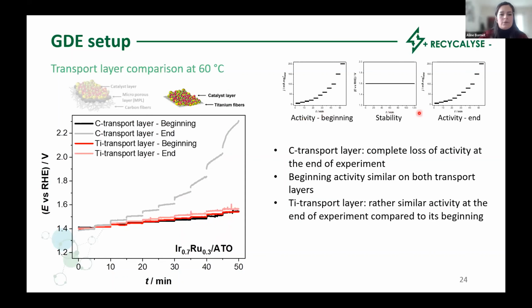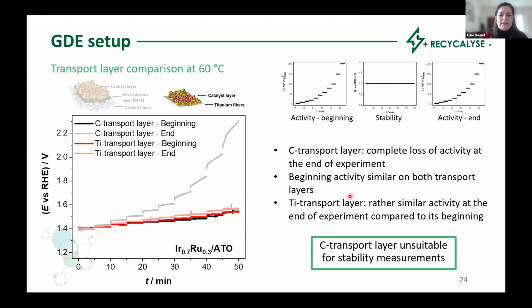Then this time, going through the entire protocol, we clearly see that the end activity is almost the same as the beginning activity. The small difference might be attributed to the ATO instability at elevated temperature, as I already pointed out earlier. And so here we can conclude that the carbon transport layer is not suitable for stability measurement, and that the titanium transport layer should be used instead.